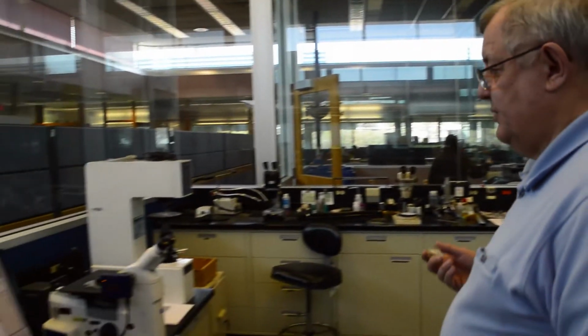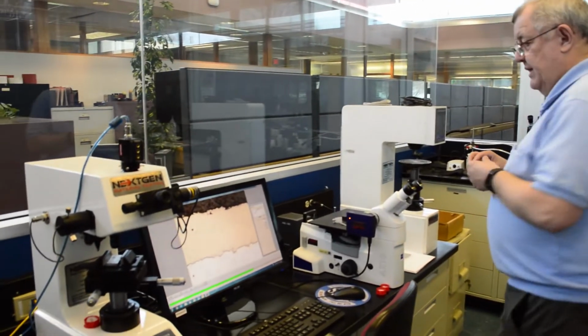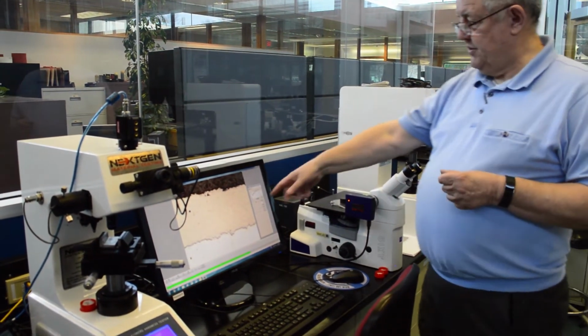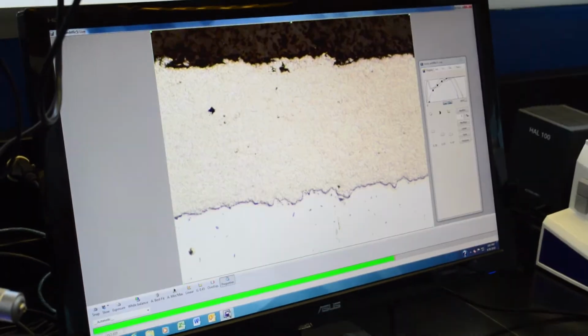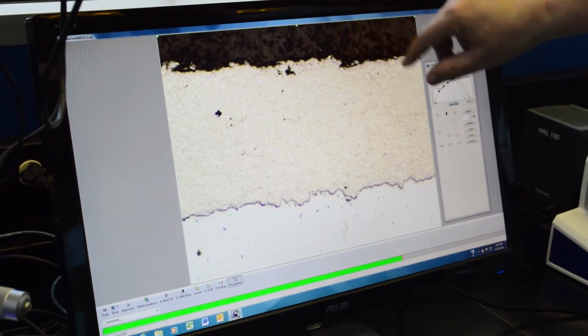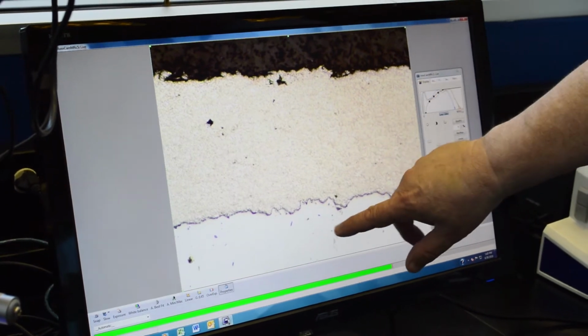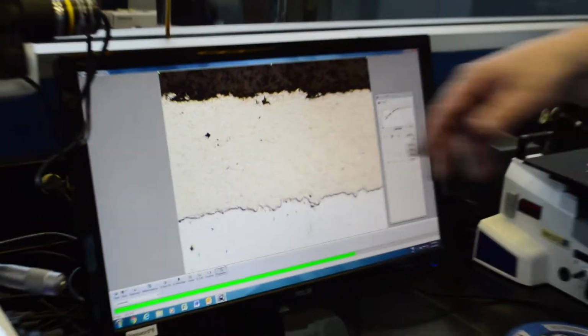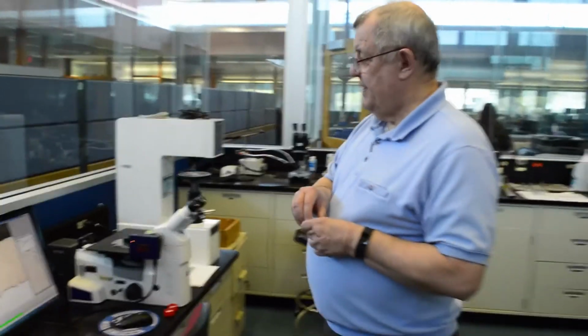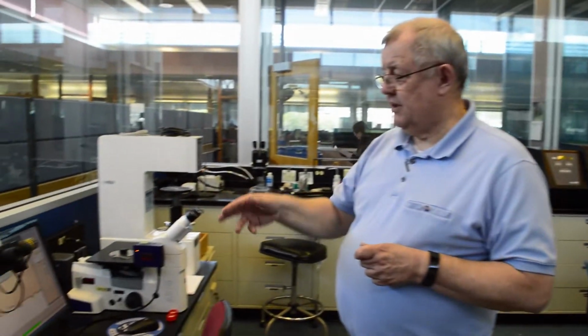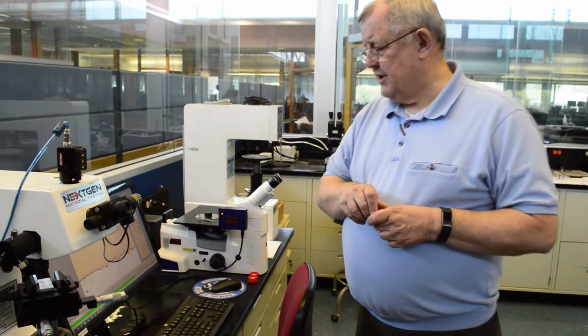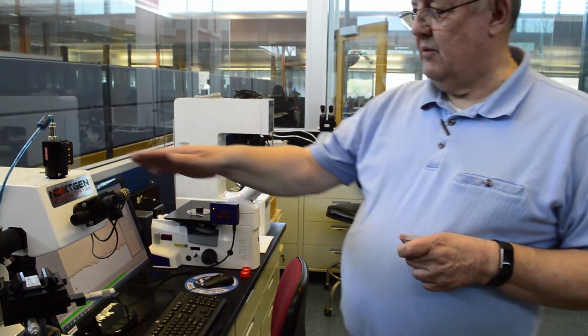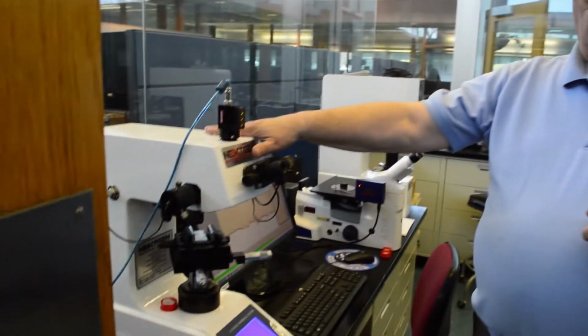Then we can go over to our metallographic microscope, and you can see a picture here of our HVOF tungsten carbide coating, showing the epoxy, the tungsten carbide, and the steel. Notice it's very low in porosity. And then we can measure porosity, we can measure RA to a certain extent. And then we can also measure hardness of the coating with the Vickers hardness tester.